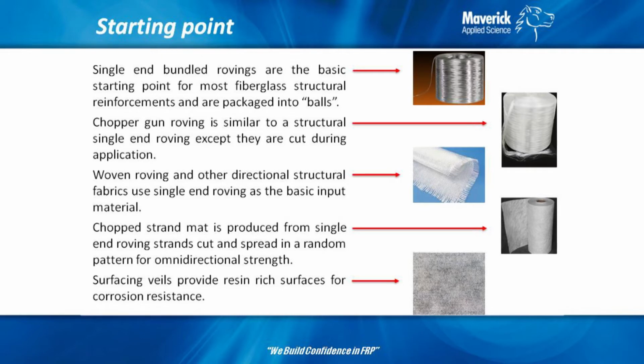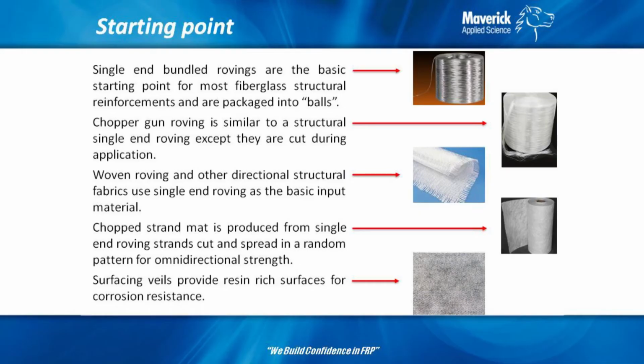The starting point of most reinforcements for fiberglass is a single end roving. The single end roving is basically glass strands that are pulled and then bundled together into a strand. The individual strands are measured in microns, so they're very small. And there's hundreds of them packaged into a string, basically, into a packaged piece of string. And then those pieces of string are used to reinforce fiberglass.